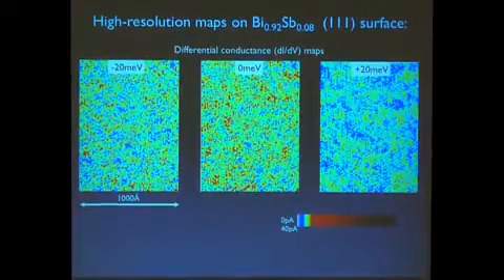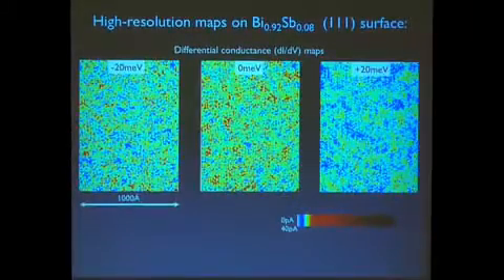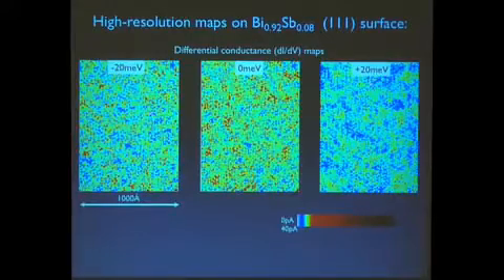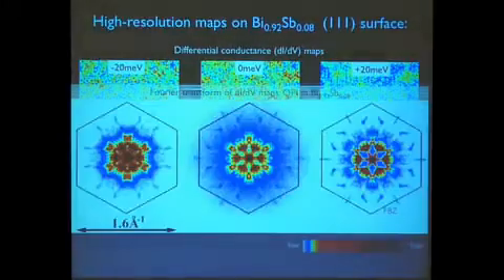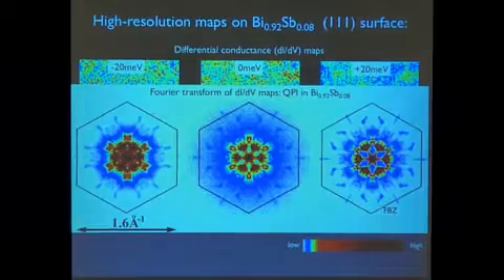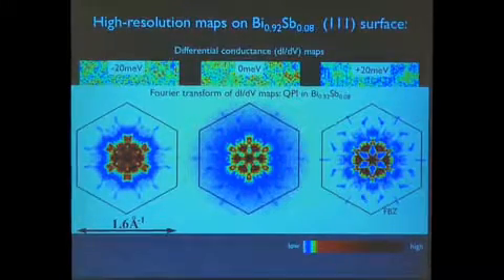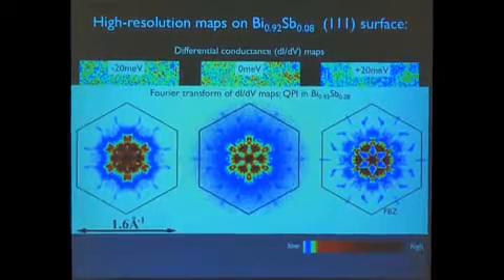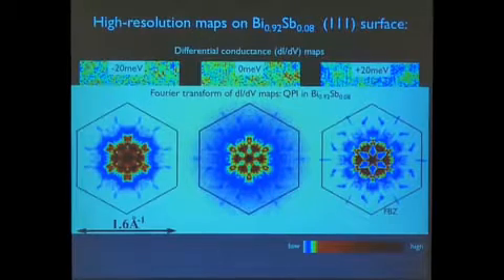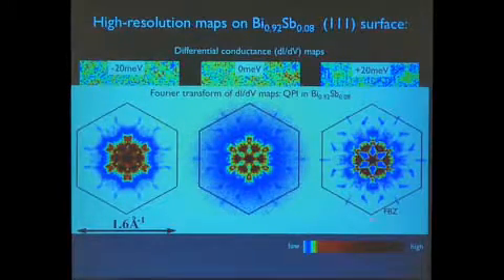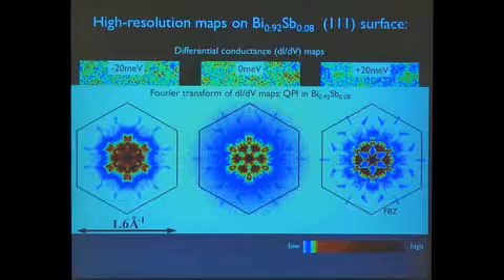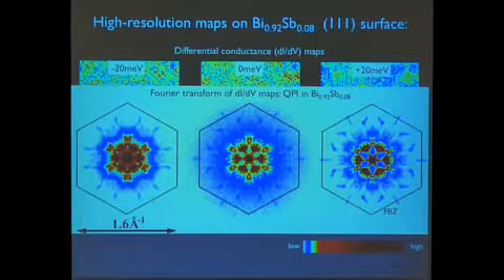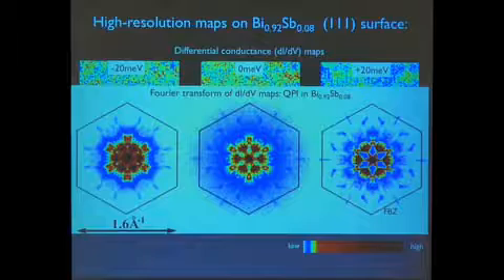that there are changes clearly. This is of the same area of the sample, looking at electrons at the chemical potential above and below. But now if I showed you the Fourier transform, you can see that there are very distinct changes in the way the electronic states of this sample Fourier transform. And basically what you're looking at are all the ways in which electronic waves can interfere with one another in real space. So this kind of perhaps looks hopeless.